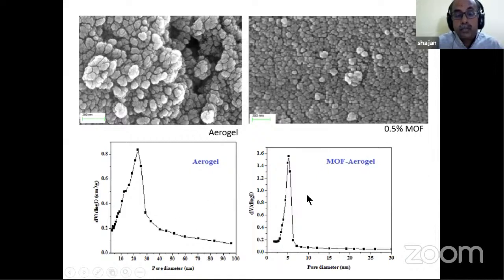You can compare this to the aerogel, where there is a broad distribution from 5 to 30 nanometers. Here it is closely distributed around 5 nanometers, and you can see in the image that almost everything has pores of equal size.